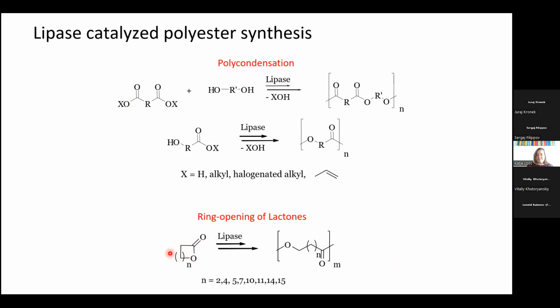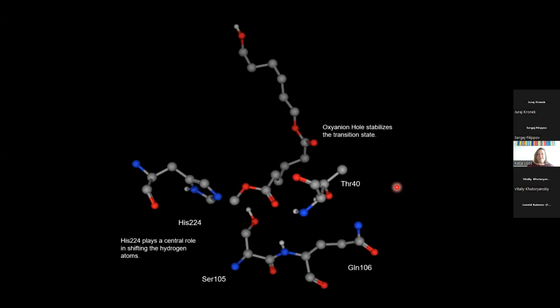It recognizes this ester bond and it cleaves it. And if you push the equilibrium to this side, then you form high molecular weight polyesters, which are an intermediate, because this n is again 15. They are intermediates between polyester and polyethylene, and have quite interesting properties. That's work from my colleagues from the Technical University of Eindhoven in the south of the Netherlands. It's also, of course, a textbook example of why enzymatic polymerizations can be interesting, because it's something that you cannot do easily with other synthesis approaches.